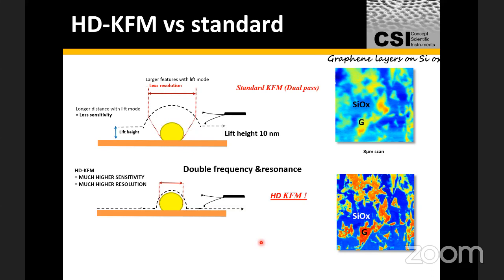in a few nanometers, and this is a nice illustration of how the instrumentation in scanning probe microscopy, when it comes to measuring electrical properties of the surfaces, has evolved over a period of 10 years, really. This is the old technique, where we would do a dual pass. So as you can see, we are only looking at the electrical signal here, and this is a graphene layer on silicon oxide. And as you can see, you have a certain resolution for the graphene, and this is really the old technique, where to measure the electrical signal.